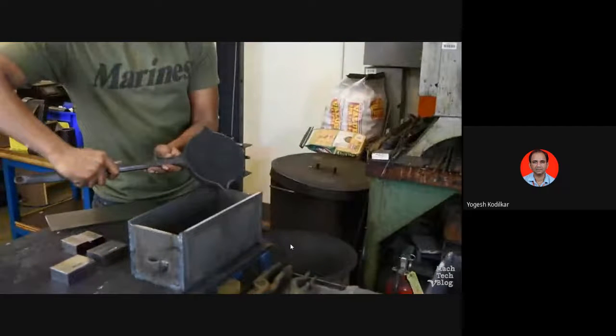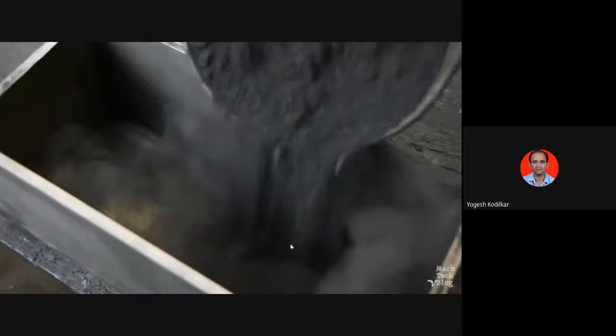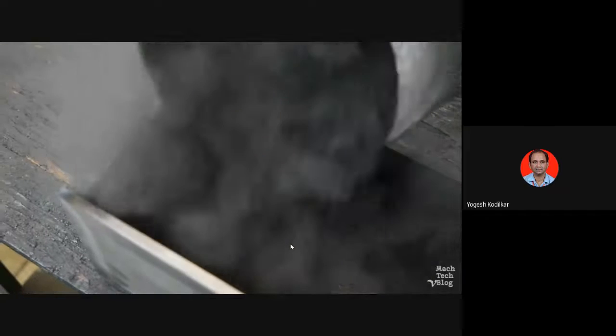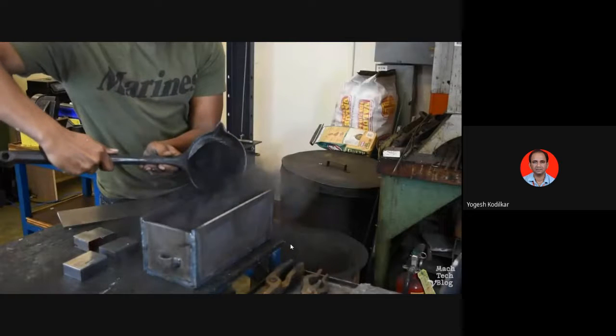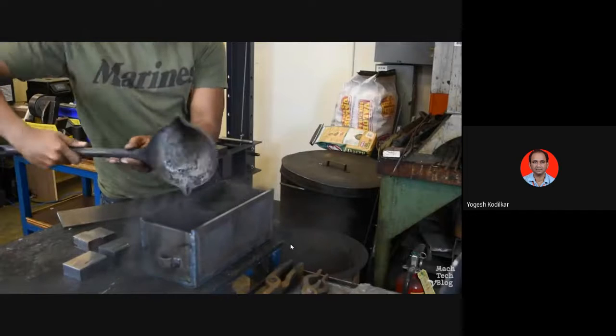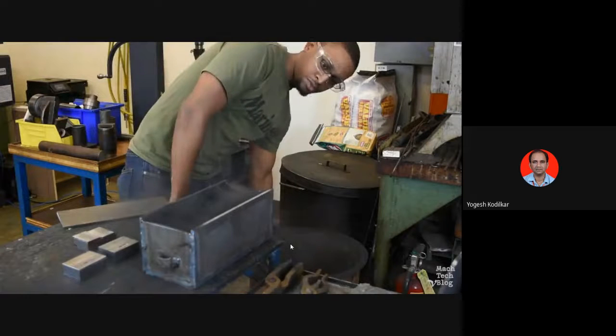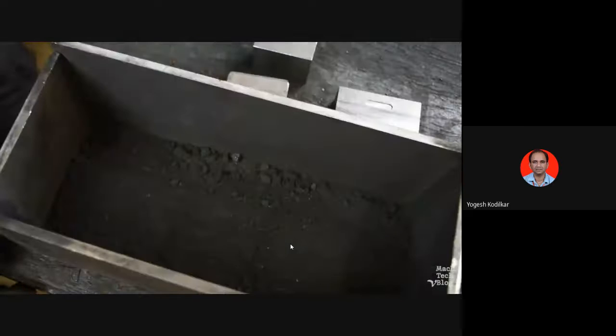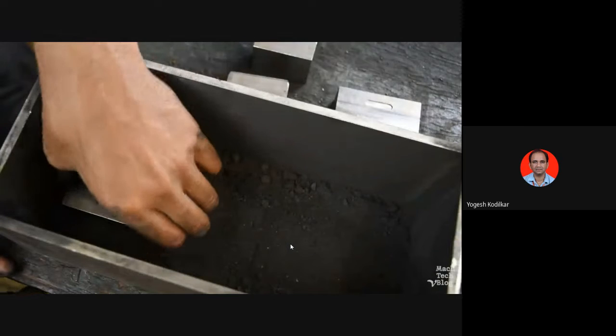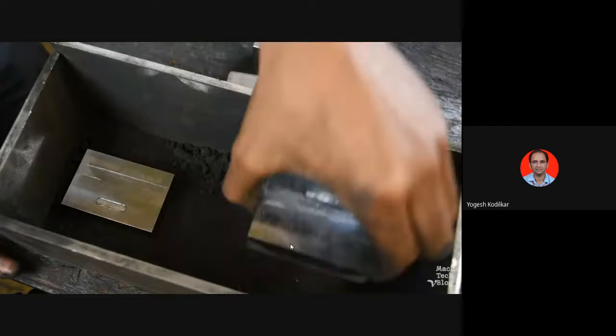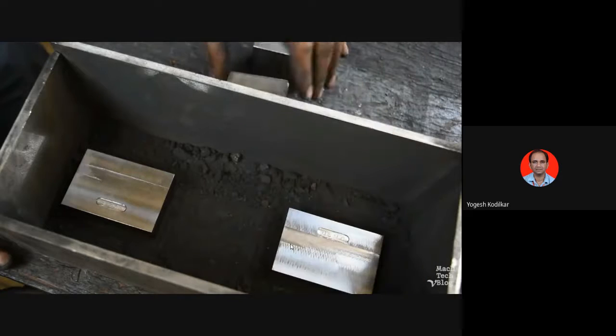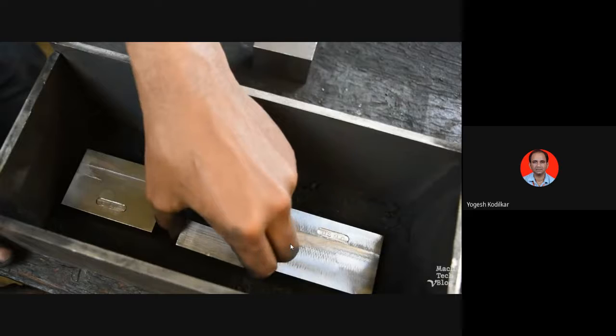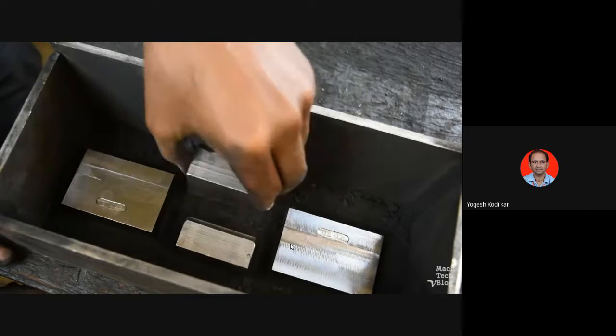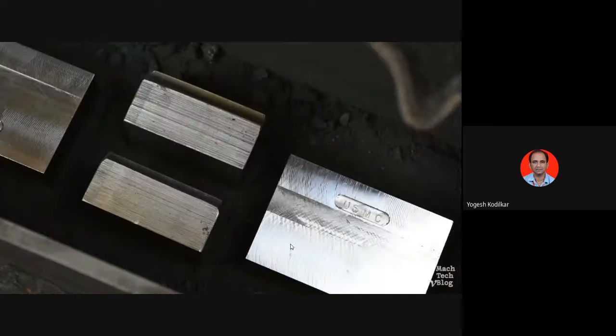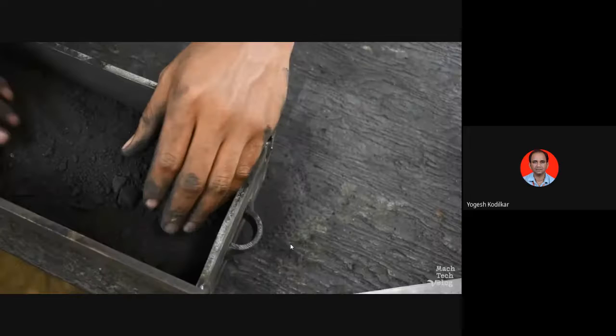Lay down about an inch of carburizing material in a steel box with a tight-fitting lid. Yes, we really are using broken-up charcoal briquettes because it actually works pretty well. Arrange the blocks so that they're not touching each other or the box. Go ahead and put in 1 or 2 pieces of 1018 steel scrap so we can test the hardness later without putting divots in the finished parts. Then pour enough carbon on top of the blocks to cover them by at least 1 inch.